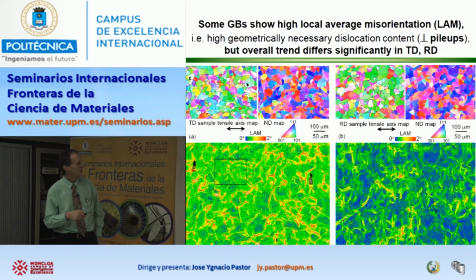But then if I compare this, this has been deformed in the transverse direction, perpendicular to the rolling direction. And this one has been deformed in the same direction as the rolling direction. And it looks completely different in terms of the distribution. There's lots of dark blue here. There's hardly any dark blue.